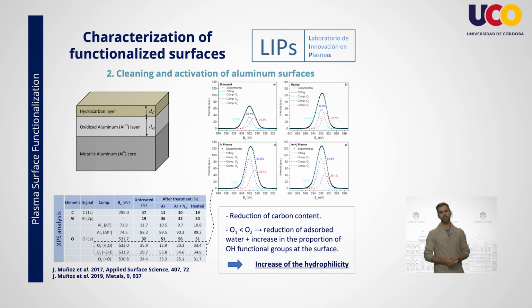For the sake of clarity, a fitting of the aluminum and oxygen peaks has been made, allowing a more detailed study of the chemical environment. Although no considerable differences were seen in the aluminum signal, this was not the case for the oxygen. The experimental oxygen signal can be deconvoluted into three main components. The first one is related to the presence of water in the surface, the second one is due to the presence of hydrophilic hydroxide groups, and the third one is attributed to oxide groups in aluminum oxide.